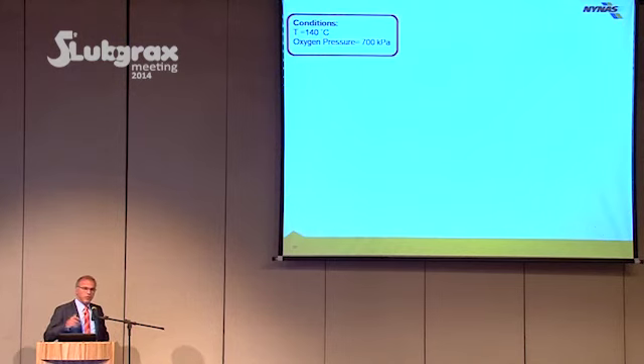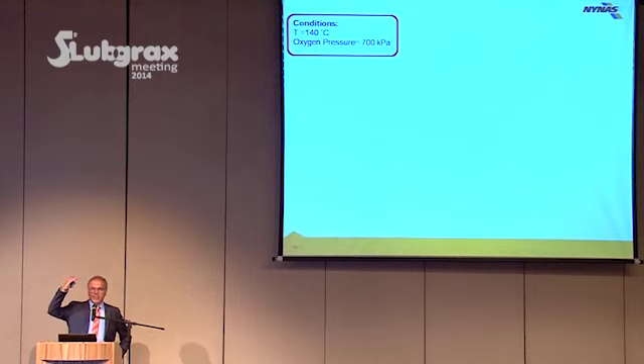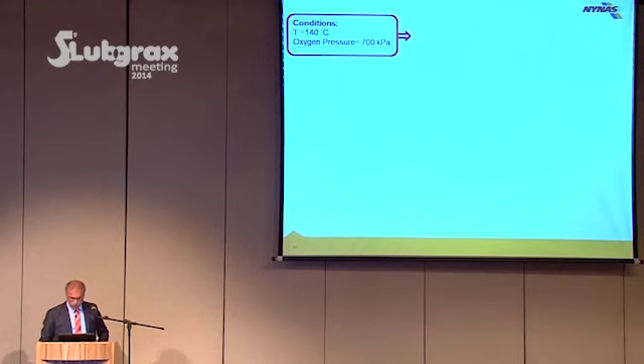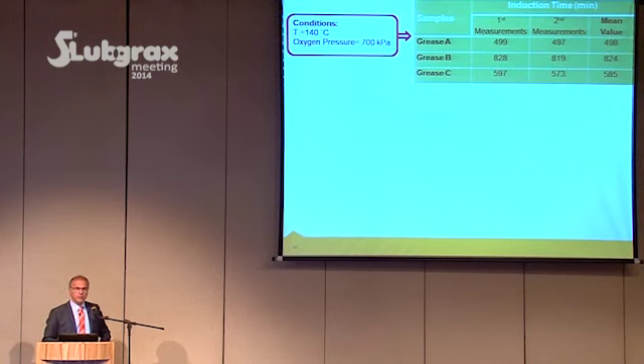So this is the condition. The temperature was 140 degrees C, and the oxygen pressure applied was 700. The test stops as soon as the pressure drops 10% below 700 kilopascal, and then they read off the time, the induction time. For these products which we presented to you, the lowest mean value was 500 and the highest was about 800. It's good to compare with the references.